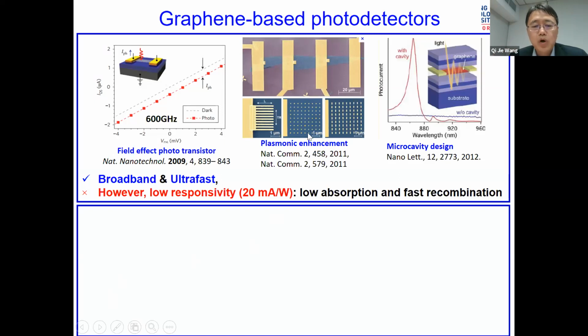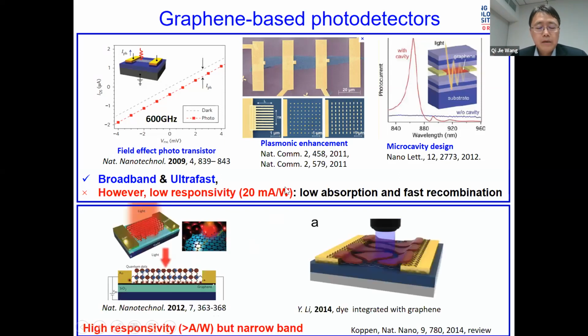And people use plasmonic structures or cavities to enhance the absorption of light in graphene. However, the responsivity is still quite low. Another approach is to use a so-called hybrid structure, where nanoparticles are placed on top of the graphene layer, still in this FET configuration.